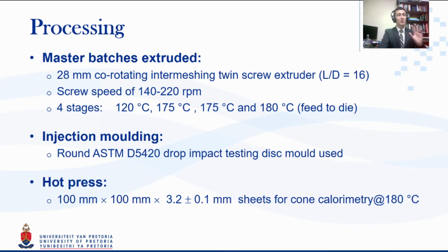The next slide, once again, is just how we made the materials. But what I want to highlight here is that with the injection molding, we specifically decided to use a very generalized ASTM D5420 drop impact test disc mold to produce our open flame fire testing samples. The benefit of this is that any university around the world that does mechanical testing on plastic materials will generally have this mold. And this test can thus be used anywhere to assess different materials against each other. This is a very robust test that would allow, at a very cheap level, to test materials.